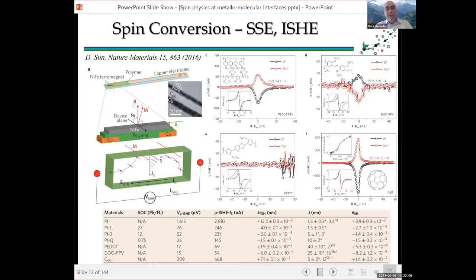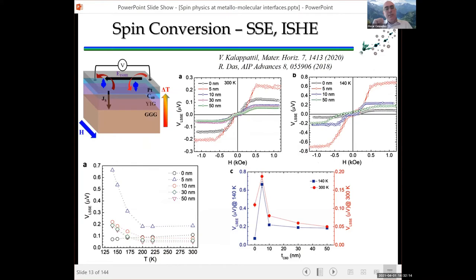Measurements with C60 in spintronics also include work from the group at the University of South Florida, Srikanth, where they did spin Seebeck effect measurements. So the spin Seebeck effect is where you generate the spin current by a change in temperature. That spin current then generates a voltage. So it's similar to the Seebeck effect in that you have a voltage induced by a thermal gradient, but the difference is here you have the spin contribution from the different chemical potentials of spin up and spin down.